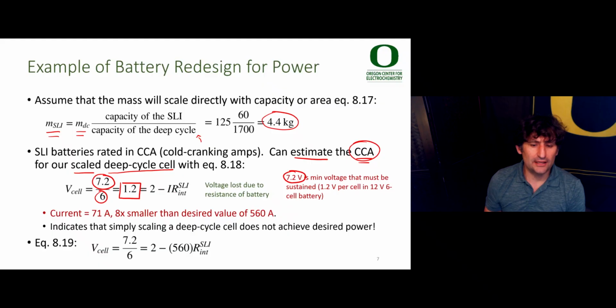So if you calculate what I is when R internal equals 11.3 milliohms, like we calculated on the previous slide, you find that the maximum current you can get out is only about 71 amps. And in this particular example, Fuller and Harb make the point that this is actually 8 times smaller than what the desired value is for this application.